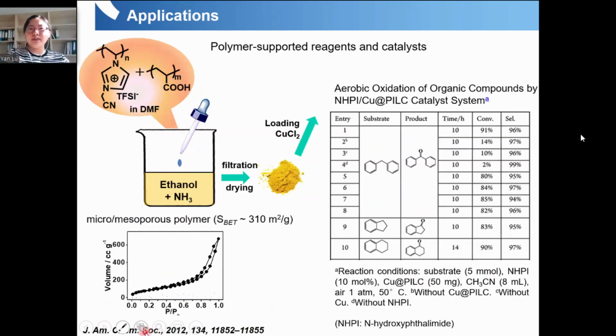Another example I would like to show you is that you can, of course, use this porous polymer as a support for catalytic applications. In this case, you can again use this polymeric ionic liquid, and when you mix it with PAA, similarly you have this acrylic acid group, and the acid group will react with ammonia and generate a porous structure in the final powder. And so you can generate a micro and mesoporous polymer, which has a specific surface area of around 300 square meters per gram.